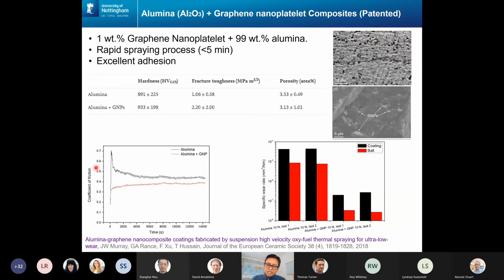Similarly, for coefficient of friction, we can drop the coefficient of friction from around 0.5 to around 0.3. And what that means is energy savings, because you're not wasting your energy by producing friction and as a consequence heat.